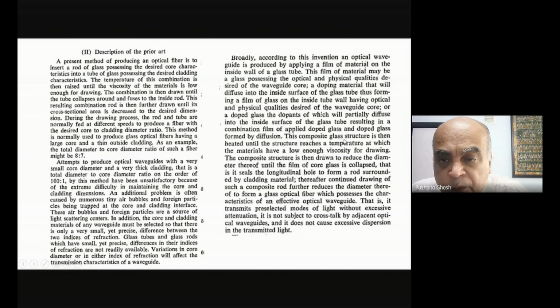This composite glass structure is then heated until it reaches a temperature at which the materials have low enough viscosity for drawing. The composite structure is then drawn to reduce the diameter thereof until the film of core glass is collapsed. So finally the rod which I am producing, the core, has no hollow there. It's a solid glass. So basically as I'm drawing, the inner film will collapse into a rod and the cladding will be over that rod.